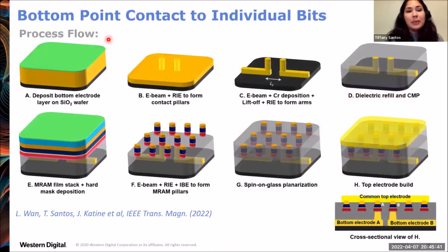Okay. But then we want to be able to make contact to our bits, and we don't have easy access to expensive CMOS. So we do what we can in our research clean room, and we made bottom point contacts. Okay, starting out with metallic individual contacts patterned by E-beam, and then another E-beam step to make the arms out to the contact pads. Then we do a dielectric refill and a chemical mechanical polishing to make the surface very, very smooth for then the MRAM stack deposition. Then the bits were patterned using the process that I described previously.